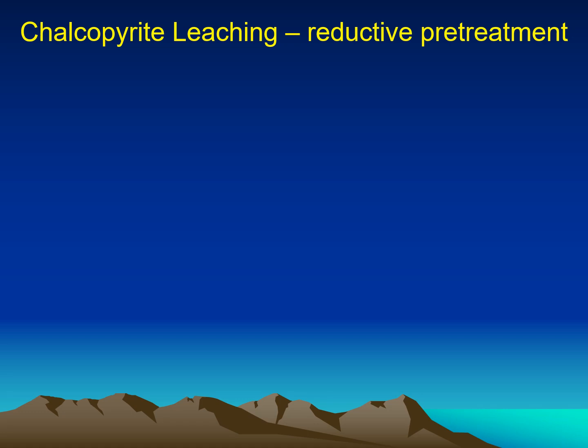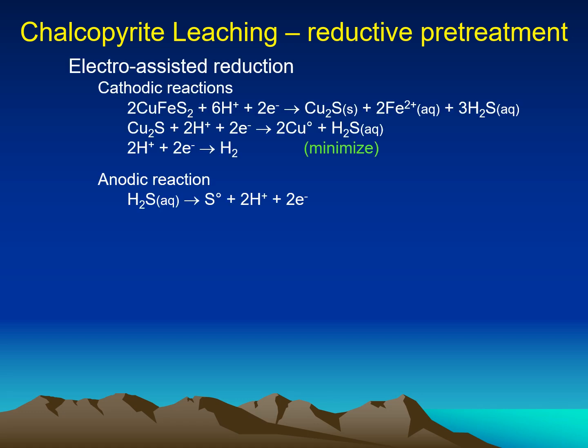The next process is chalcopyrite leaching, but this is with a reductive pretreatment. In an electrolytic cell at the cathode, chalcopyrite comes into contact and is reduced to chalcocite in the first reaction, liberating ferrous ion and hydrogen sulfide. And at the same electrode, the chalcocite is further reduced to copper metal, and more hydrogen sulfide is released. And of course, we have the parasite reaction, which should be minimized, which is the production of hydrogen. At the anode, we have the hydrogen sulfide being converted to sulfur in an oxidation reaction.